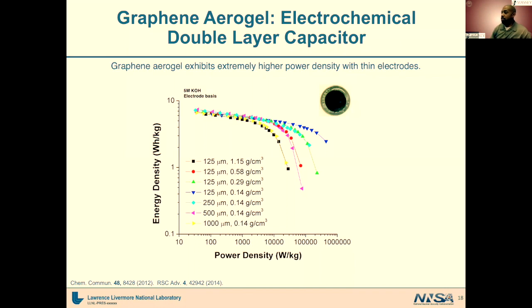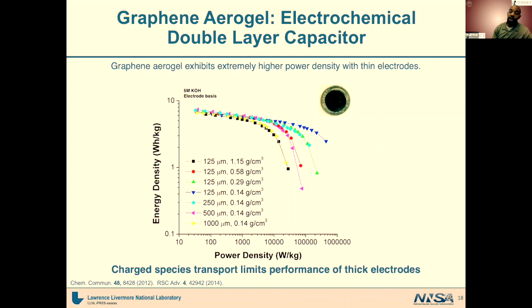And so the reason for that is that these aerogels, as I mentioned before, are not very good with transport. And in this case, it's charged species transport. As you go to thicker and thicker electrodes, you're not able to actually access all of your electrode, because in the time that you're trying to do these fast scans, your charged species are not able to get in and out of the full thickness of the electrode.